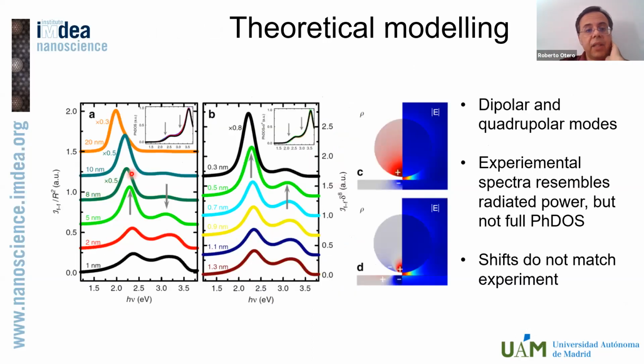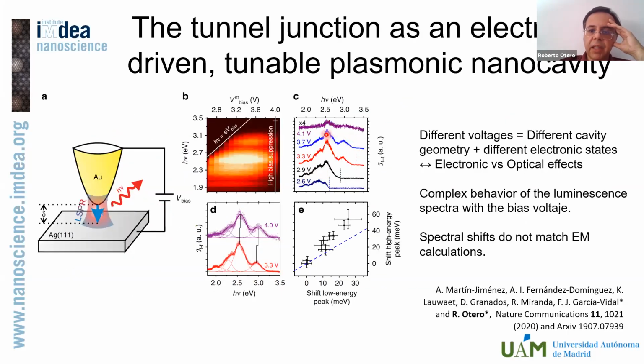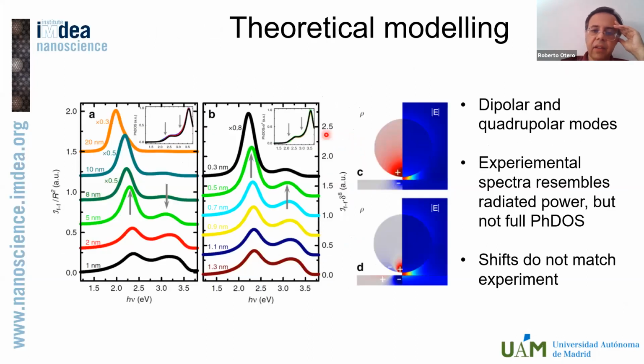We started collaborating with the group of Professor García Vidal, and basically what they did is to simulate the tip as a sphere of gold and the sample as just a flat silver surface. They place a dipole right in the middle, and then they try to calculate the radiated power with the same geometry as our experiments as a function of the energy, the radiated spectrum. What we can see is that for relatively reasonable numbers, the spectrum resembles the experimental ones quite a bit. So it shows a peak at around 2.5 and a lower peak at around 3. That's more or less what we have over here, although our experimental spectra are way richer than the theoretical ones.